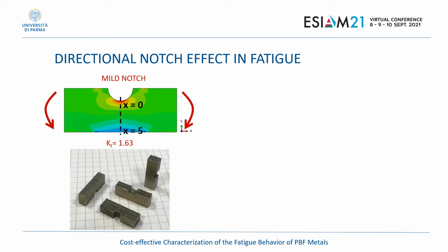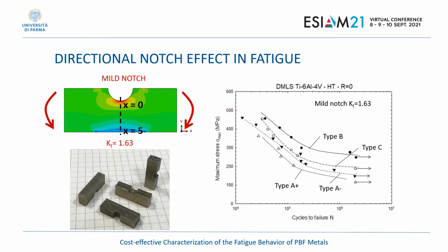So we can investigate the directional notch effect in fatigue. This diagram shows the set of data that were obtained for the four directions of the notches. You can recognize that there is a large difference between the best fatigue data and the worst fatigue data. They range from 260 for the best orientation, which is the type B orientation, to 130 for the type A plus orientation, which is the DOWNSKIN orientation of the notch.